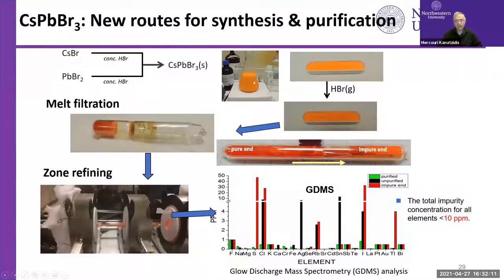This is done in solution. We can filter the solution. We can treat it with HBr gas to remove water. And then we can put it in a tube where we can melt it. And then we have a filter, and we can pass the melt from this side to that side. And you can see, even though this is a very nice reaction, it doesn't seem like it has too many impurities, but the material, even when we melt it, still has a lot of black stuff. Then we filter it, we remove it, and we use this either to do zone refining, or we can use it directly to grow a large crystal. This is 6 or 7 centimeters of material.